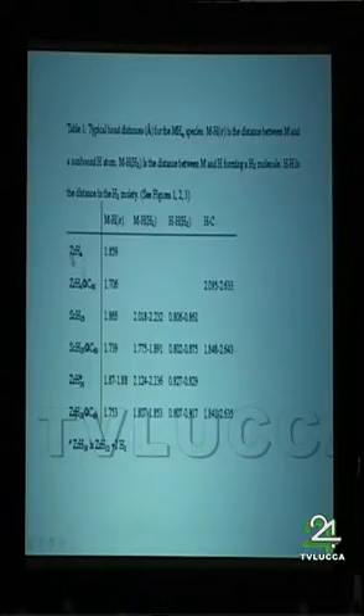So, for example, you see zirconium H4, we calculate a zirconium-hydrogen bond distance of 1.86 angstrom, while inside the fullerene cage, the zirconium-hydrogen bond distance is 1.71 angstrom. So it's about 0.15 angstrom shorter. And then the same works for scandium H15, 1.87 versus 1.74. And also, for example, zirconium H16.